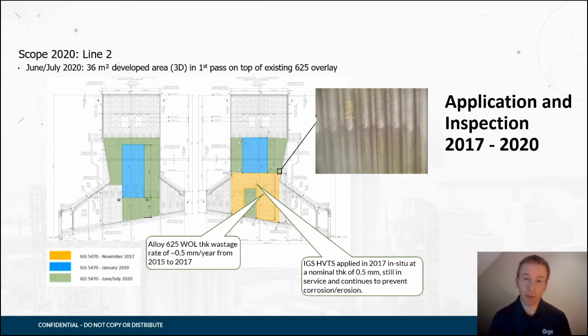So this is after 3 years of operation inside these boilers. What we were able to see was that there had been no degradation, no breakdown of the installed high velocity thermal spray cladding in the same areas where prior to that the client was measuring a loss of up to 0.5 millimeter in certain locations of the 625 overlay. That overlay was originally installed in 2015 at 3 millimeters thickness. So they would have lost that protection and potentially lost those tubes within 18 months if they hadn't installed the high velocity thermal spray protection system. Over the 3 years that it has been in service, there was no measurable loss of material. The weld overlay underneath is still maintained at the same thickness, the tube integrity is still there, and the thermal spray is still able to operate.